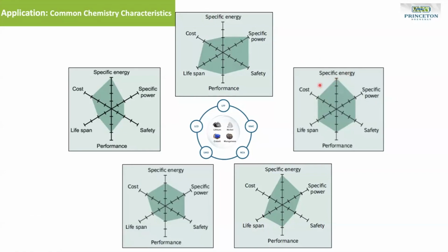So from here, you can see it's very high energy density. So that's why most EVs in the US use this material. The challenge is that this material is more expensive, because obviously cobalt and nickel are more expensive than iron phosphate. And also lifetime, you can charge maybe a few thousand times, but not going to 10,000 times or even more. And also safety is a little bit of a challenge for this material. You can see most of the challenge for EV batteries is basically burning because of these materials. But people really enjoy the high energy density.